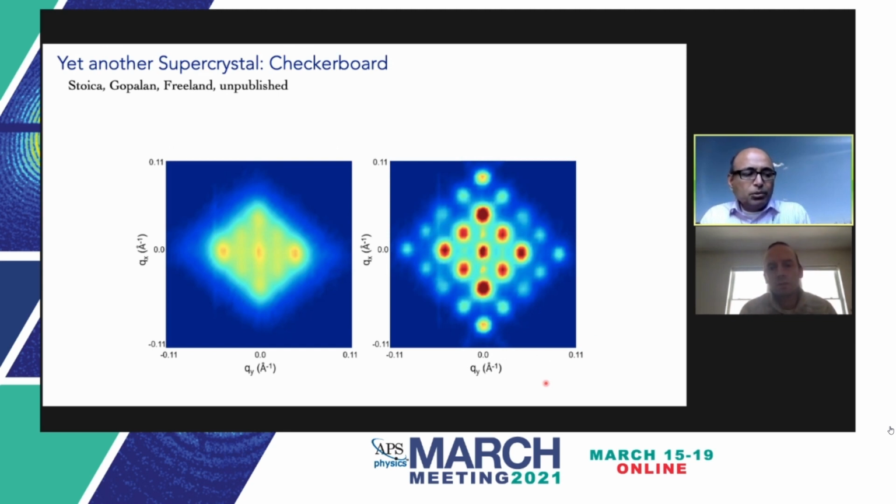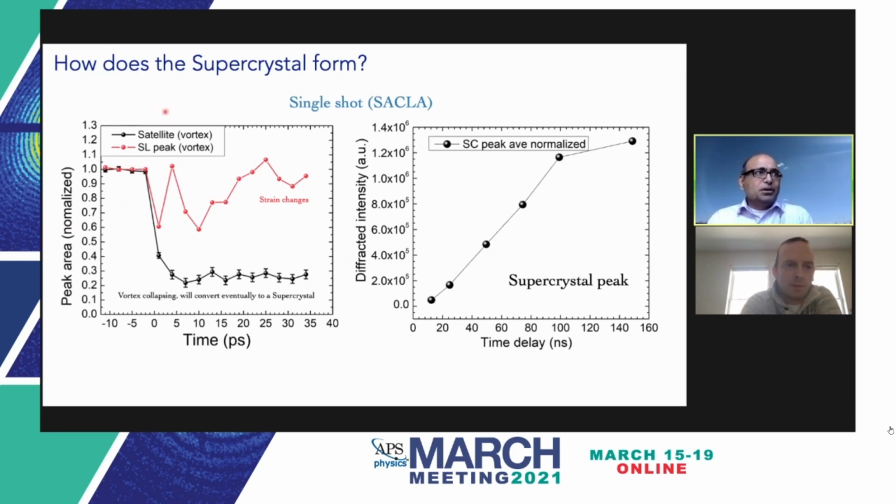phase. The other point I would like to make that we have explored is the non-equilibrium part. It turns out that the pulses have to be short. If they get to 1 to 10 picoseconds or beyond, then we can't create this supercrystal anymore. And so you have to deliver that charge, but you have to deliver it in a short period of time, very quickly. You have to shock the system. And as you can see towards the end, I was showing how the system responds within a picosecond. It has collapsed, but it might be even faster than that. We don't know what else is happening on this ultra fast time scale, like femtosecond time scale. So it seems like time is another important variable in trying to find new ground state or new metastable states.